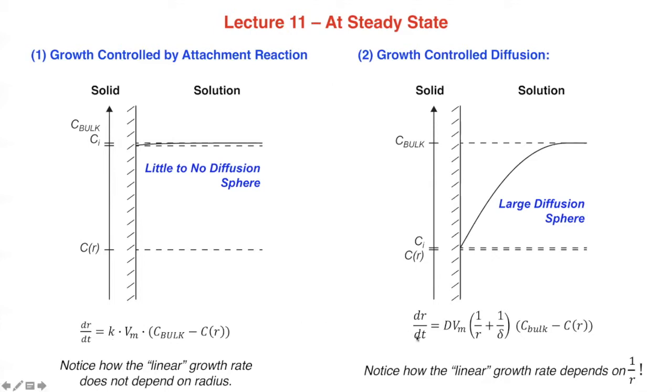And so that means that under diffusion controlled conditions, small crystals grow faster, and you can get a phenomenon called size distribution focusing. Normally I would talk more about this, but we just ran out of time. But I will say that the only established mechanism for size distribution focusing relies on this diffusion limited growth mechanism.